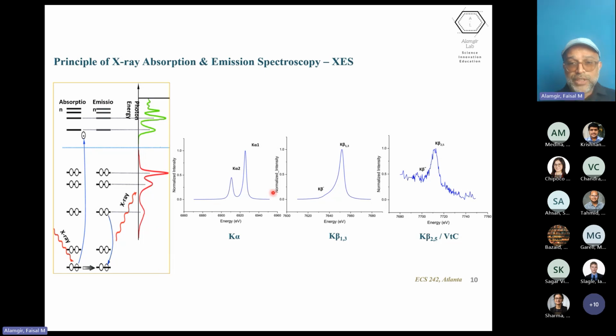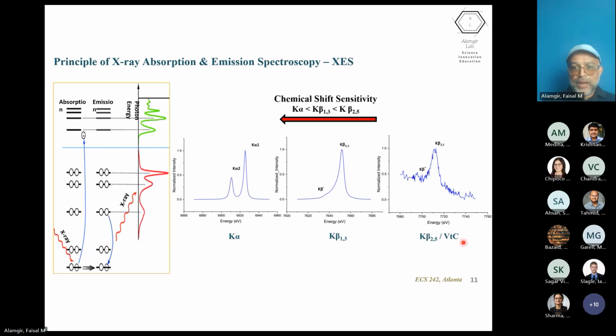So we have actually a lot of choices of the type of emissions that we can use. And the most intense ones are the so-called alpha emissions, and followed by the beta emissions. And within the beta, there's an even smaller subset of beta that is the lowest cross section, but carries a lot of very interesting information. And that would be from the valence electrons down to the core, the so-called valence to core emissions. All right, so chemical sensitivity goes up as you go from left to right, but the intensity, the cross section, is higher when you go from the right to left.